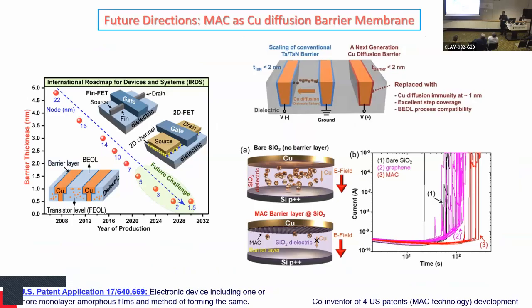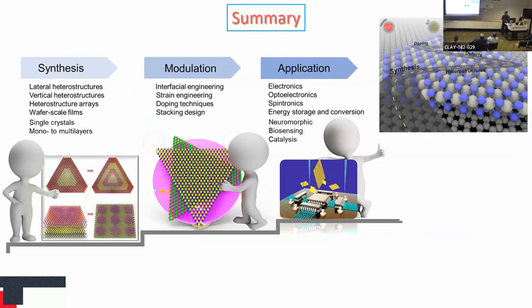Another thing is that we can use it in electronic devices. Normally, copper diffusion is one of the big problems. Copper can diffuse into the dielectrics and short the device. So we can use this kind of material as a barrier layer. We can put it on the copper and it will restrict any copper diffusion into the device. This is one of the projects we previously did with one of the NESTI partners. And that's all from my side.